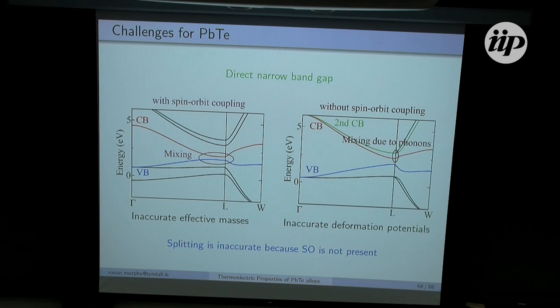Now, going back a little bit, I want to talk about what happens to the electronic band structure if you neglect spin-orbit coupling. In this case, we do capture a positive band gap, but the splitting between the first and second conduction band energies is inaccurate, and there's a little bit of mixing here. Deformation potentials here are what we plug back in to calculate our intravalley acoustic scattering rates, and these are going to be inaccurate in this case.